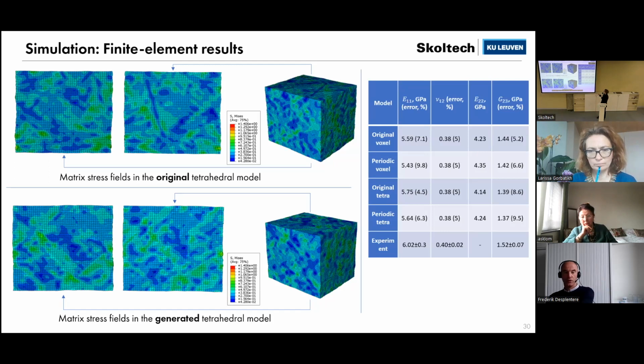If we move to the results of simulation, we can see that the original voxel models were able to present better results when compared to experiments. In my opinion, there could be different reasons for this. One reason is that in the representative volume element size determination, the size was taken too large to have periodic boundary condition effects. The second reason is that fiber and matrix properties could also have been taken not so well. For example, if we increase the property of the matrix, it can increase both the original and periodic results, and in this case the periodic results would be closer to the experimental one, but it needs further investigation, and we are already working on it.